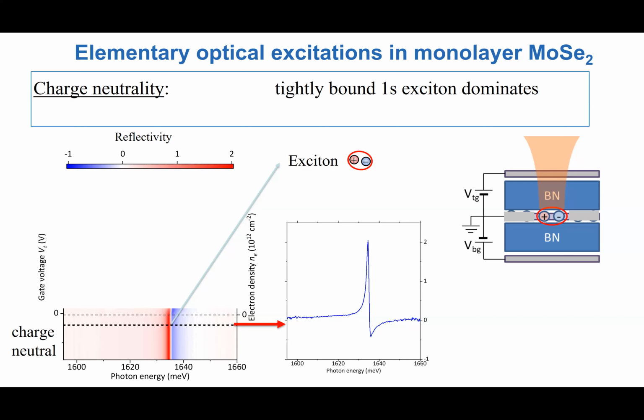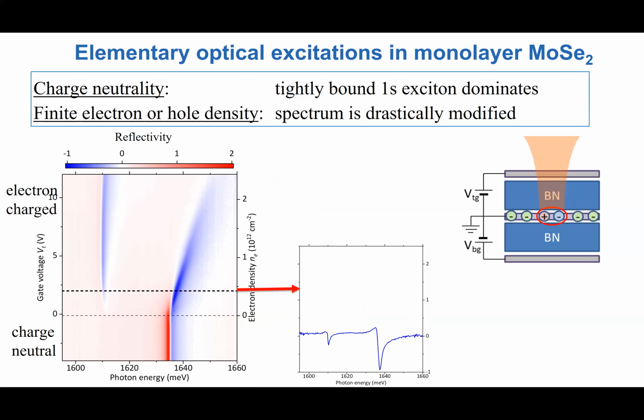Okay, so this is the easy part. You can think of this as simple linear physics. Then what happens is that when you introduce electrons into the system by changing the gate voltage, you see that the spectrum changes dramatically. And again, Antonio explained this nicely yesterday, but if we dwell on it, if you take a line cut here, you see two things. First of all, some of the oscillator strength from this exciton line is transferred to a new resonance. And the exciton line blue shifts and broadens, whereas as we increase the density, the lower resonance picks up more oscillator strength. So how do we understand what's going on here?